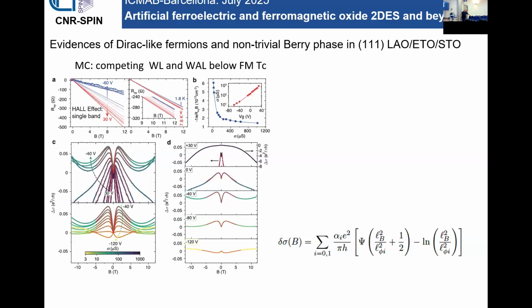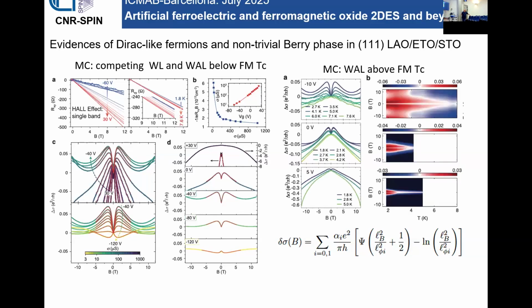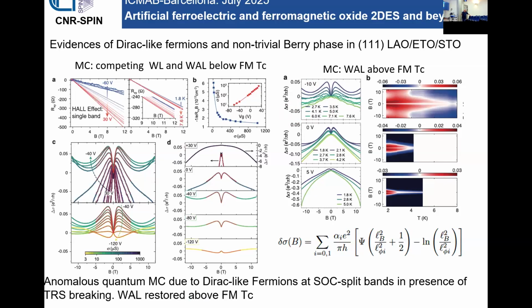Now, another proof that this is probably true is that we also performed a temperature dependence measurement of this magnetoconductance. And when we cross the ferromagnetic TC, which in this system is relatively low, between 6 and 8 Kelvin usually, the anomaly disappears and only weak anti-localization remains in the magnetoconductance correction. So we believe that this system is an example where Dirac-like fermions are formed in spin-orbit coupling split bands in presence of time reversal symmetry breaking.